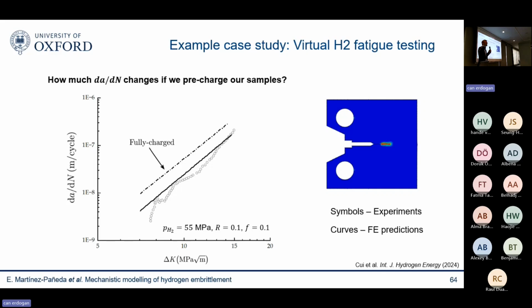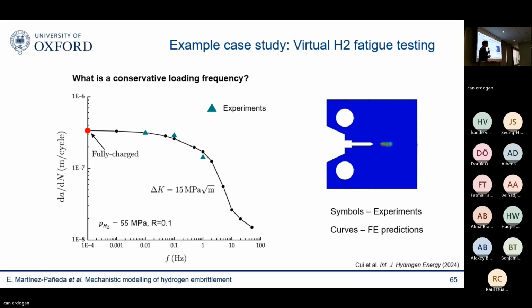So it's up to you as an engineer to decide whether this is a big change or a small change. Then the other thing, of course, we were very interested in is changing the frequency. In the real application, we work at very low frequencies, but experiments are done at high frequencies. So we are able to do that with the model, and sometimes they run experiments at low frequencies. So we were able to actually show that the model agrees quite well with experiments at low frequencies, and we were able to predict what happens in the regime where they're going to basically be running their pipelines and pressure vessels.